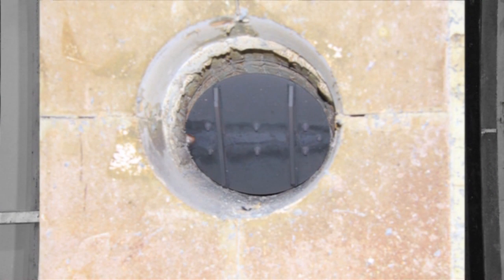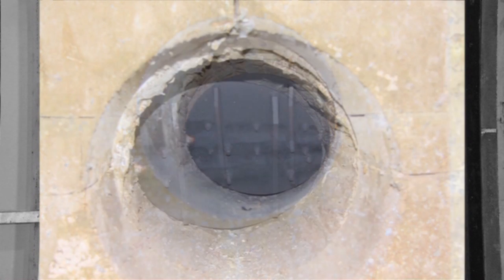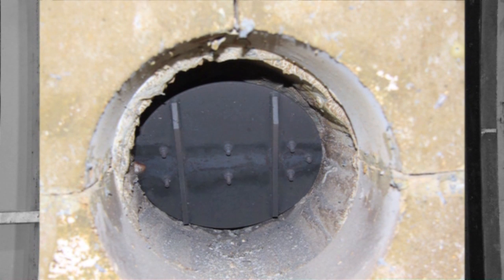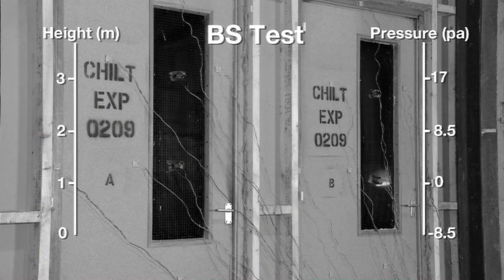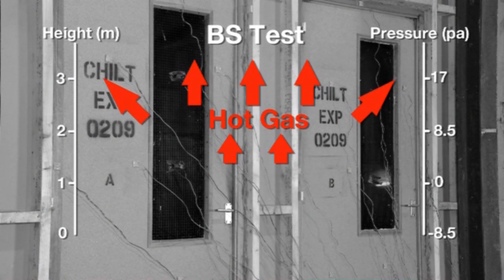Using dampers in the furnace flues, the pressure is also controlled to follow the requirements of the relevant test standard. To give a representation of conditions in a real fire, the standards specify that the furnace pressure must be positive towards the top of the furnace, pushing flames and hot gases through any gaps in the specimen, but negative towards the bottom of the furnace, drawing air into the furnace through any gaps in the specimen.